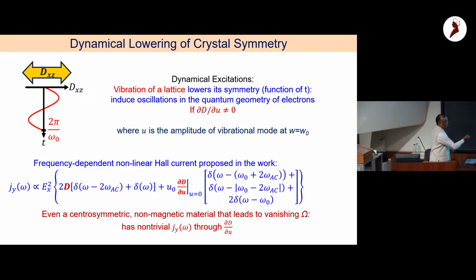And indeed, if this is non-zero, what we work out, again with very simple mathematics, is that you get a Hall effect at twice the frequency, like the nonlinear Hall effect. The first term is exactly what Liang Fu and Sodemann showed. But the second part is what we are proposing, and that depends on the derivative of the Berry curvature dipole with respect to the phonon. You will get peaks at these various frequencies. These are operating AC frequencies, 2 times omega AC, modulated with plus omega naught and minus omega naught. And because of rectification, you will also have a peak at omega naught. So even a centrosymmetric, non-magnetic system, in our proposal, can have non-trivial Berry curvature induced, because dynamically one can lower the symmetry.